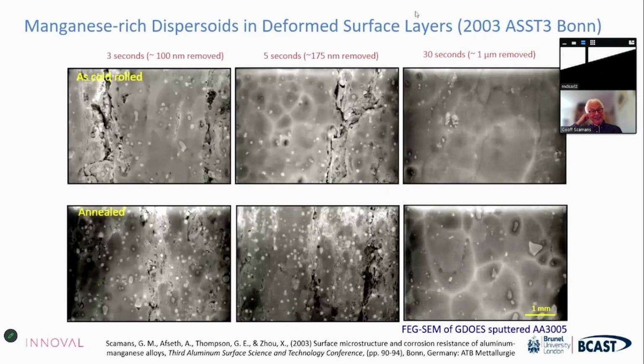And it was very simple to explain what was going on, because within the deformed surface layer, there's so much stored energy in these systems, in such a fine grain size and such high rates of diffusion, particularly along the grain boundaries, you can actually get a lot of things going on in these layers that don't happen in the bulk. What happens during the annealing process is you're precipitating high quantities of manganese-rich dispersoids, and these provide the cathodic sites to accelerate the corrosion reaction and to promote the filiform corrosion.